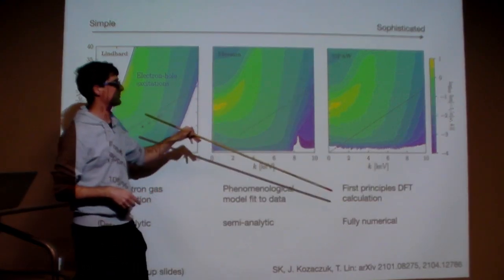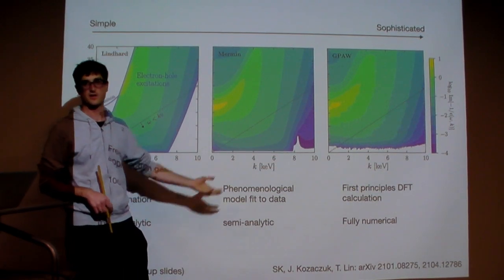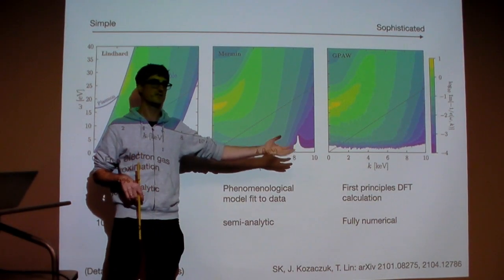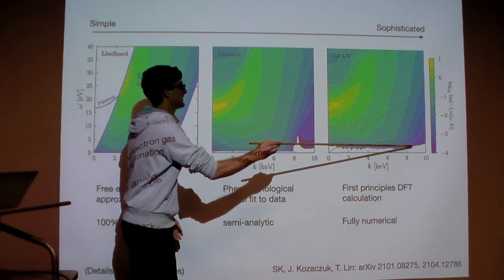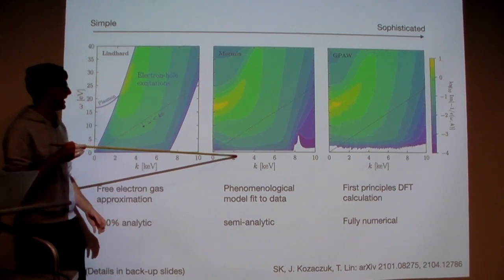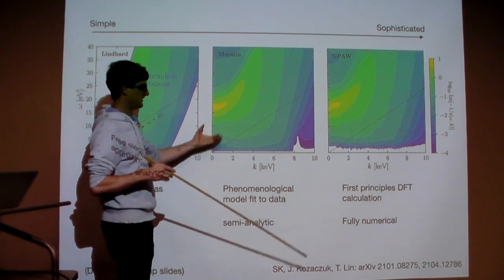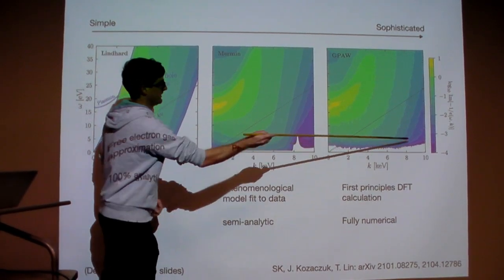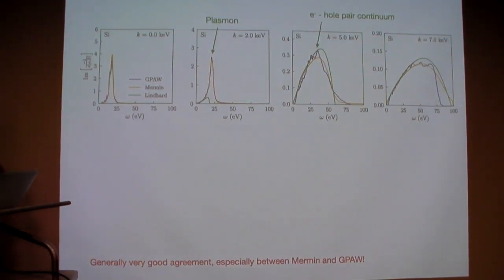This is if you do a density functional theory calculation. You could also just say, okay, I'm just going to run this code. I'm just going to calculate this on my supercomputer. It's going to take a week, but then in the end I'll have an answer. And then you can get the band gap explicitly. This particular version does a pretty poor job on the band gap. There exist versions where this is included, but in this one that we used it doesn't. So basically this is the fanciest one that we have at the moment.